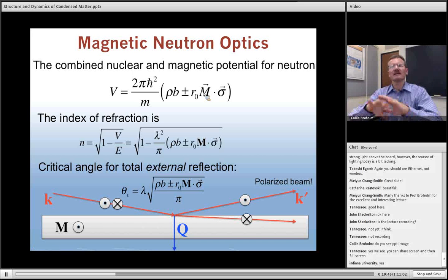And so now, you remember when we talked about the smeared nuclear potential, I said that it was akin to an electromagnetic description where we are always averaging typically over some appropriate length scale. And likewise, when we talk about the dipole-dipole interaction, now I'm not going to be concerned about the particular distribution of dipole moments from site to site in the sample, but I'm going to talk about a smeared dipole moment distribution. And of course, the appropriate description of that is in terms of the magnetization density.